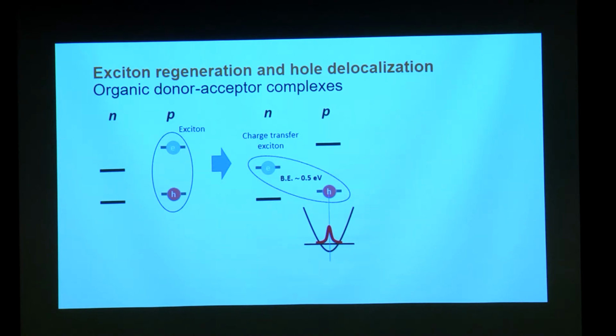But you see, one of the mysteries of organic solar cells was that even in the charge transfer exciton state, the binding energy used to be about half an eV. And if that were the case, there was no way we could separate them to get electricity. But the solar cells work, because you shine light and you get free carriers as electricity. The question was, how did we break the charge transfer exciton, even though its binding energy is significantly large compared to room temperature, which is 25 millielectron volts?